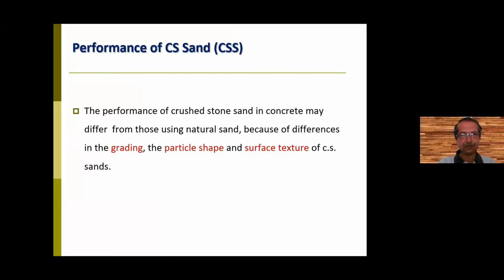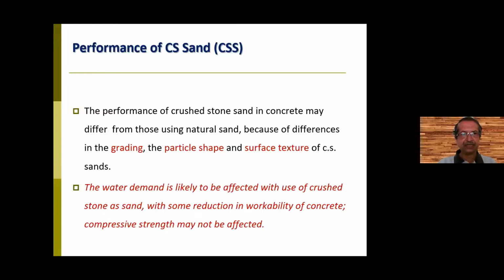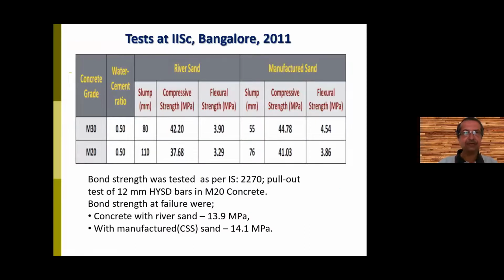So for the performance of crushed stone sand, you have to be very, very watchful about the grading, particle shape and surface texture. And the water demand is likely to be affected because crushed stone sand is actually a very bone dry material. River sand has a certain amount of water which is already absorbed or which is there. So it is almost like a saturated surface dry kind of condition, whereas this will have absolute dryness. So if you don't take care of this, your water cement ratio can go for a toss and you may have issues. If it is extra, then compressive strength may get affected. But if you take care, definitely you can get very good strength from the crushed stone sand made concrete or sand.